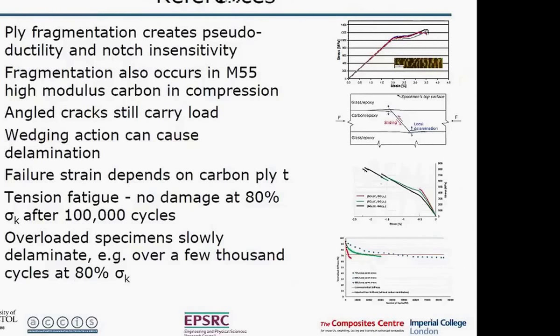Did you look at the bonding between layers? I suppose in your numerical analysis, you assume there's full bonding between glass and carbon. Yeah, with these particular materials, in all cases, we didn't see any problems with the bonding, even though there were different types of epoxy. We did fracture tests, for example, to assess the G2C, which is pretty critical, and they behaved pretty similarly, with a G2C somewhere around the bound between the G2C of the initial basic materials.